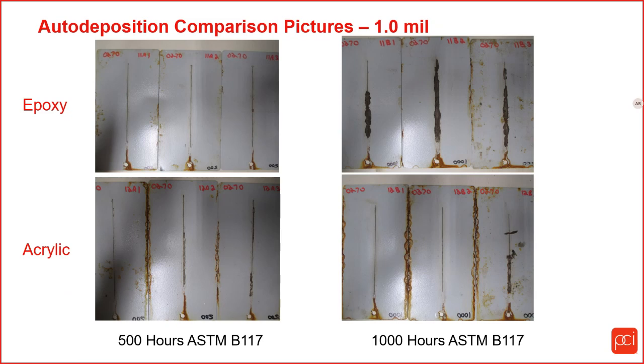The epoxy and acrylic auto deposition at 500 hours, you can see there's minimal difference, but there is a little bit of difference: the acrylic has a little bit more scribe creep back than the epoxy. And you can see at 1,000 hours that the epoxy had quite a bit more scribe creep back than the acrylic.